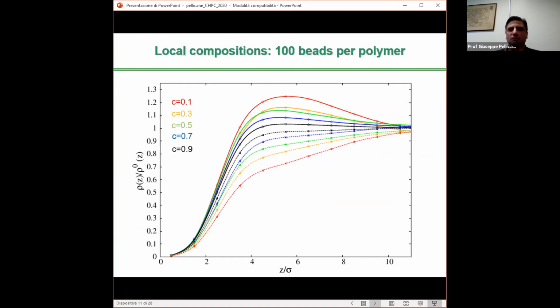When we consider the case of longer chains, this time cyclic polymers get more adsorbed at the interface, and for all the compositions of the mixture, as is shown in this slide, in quite good agreement with the prediction of the self-consistent field theory. In this slide, the full lines are for the density profile for the linear polymers, while the dashed lines are for the cyclic polymers.